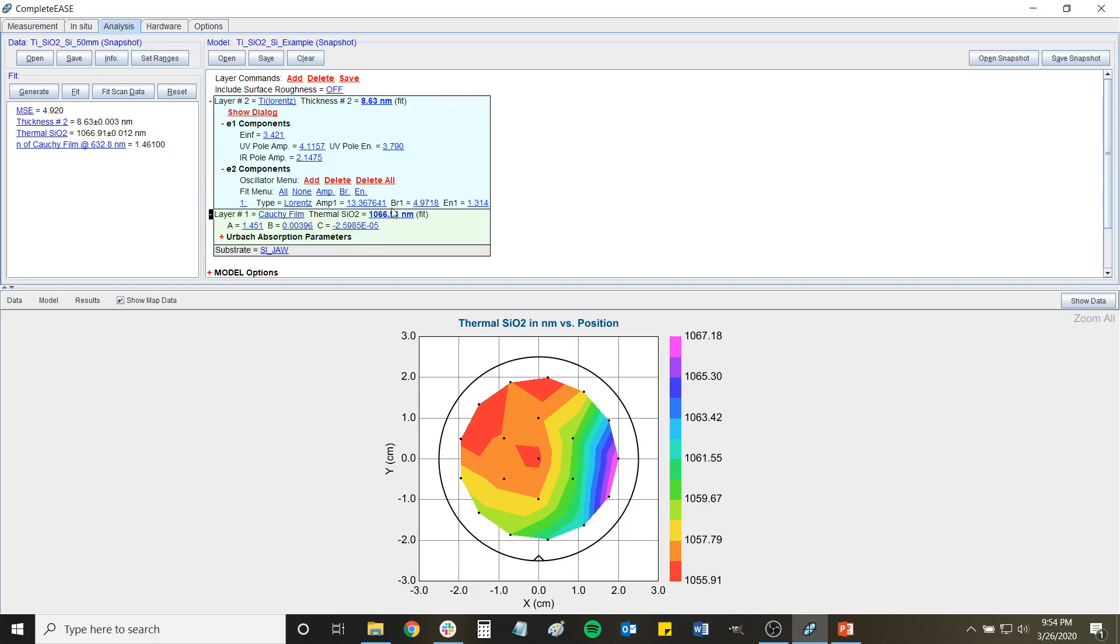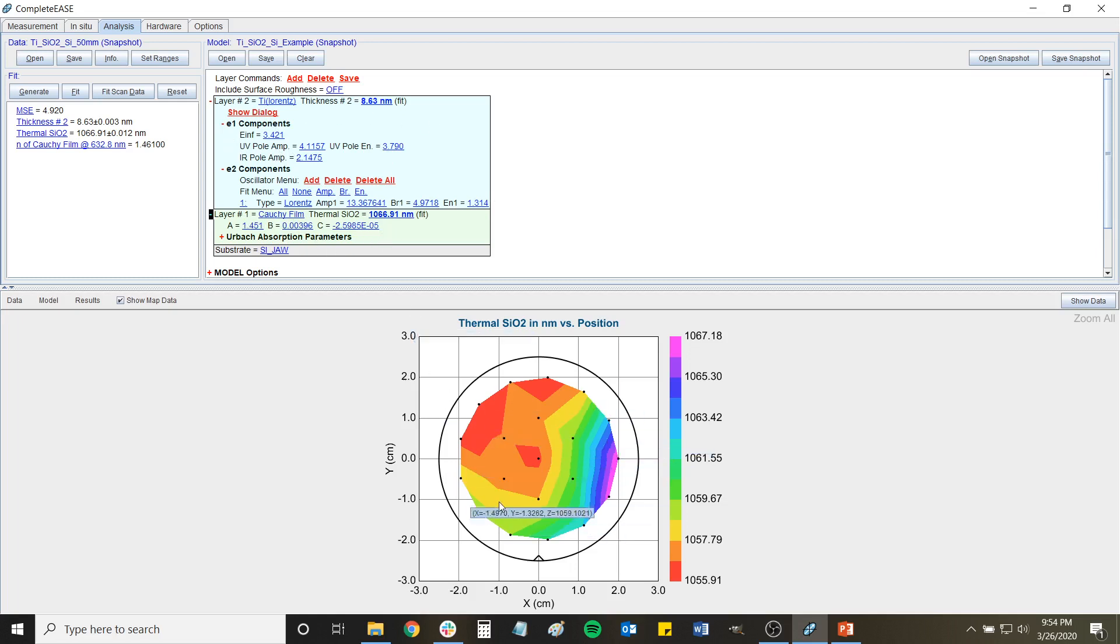So these different layers that I'm dealing with, I'm only fitting the thickness. The other values that describe the optical properties that the material has, I've left those in place and I've left them alone. But I gathered these much like how you'd imagine - I just fit the Cauchy film and did a map scan.